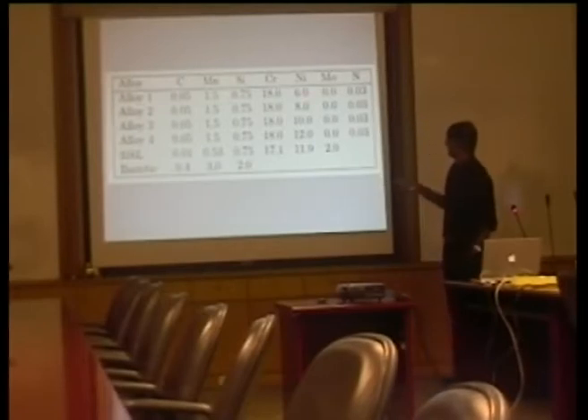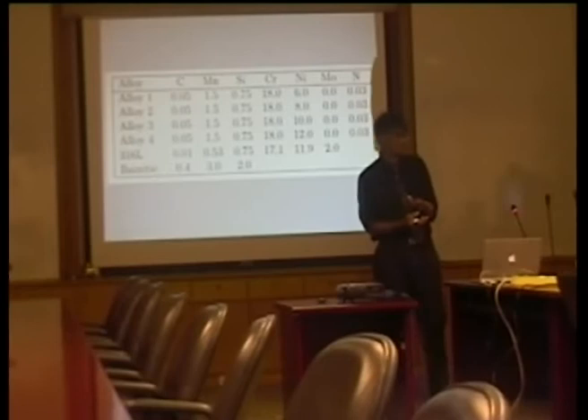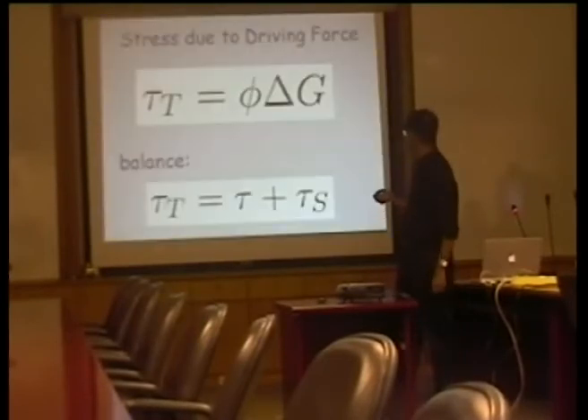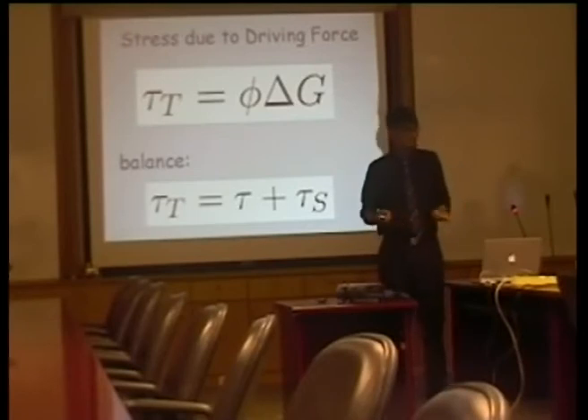So it's very powerful. Bear in mind that here all I'm doing by altering the nickel concentration is making martensitic transformation more difficult, because as I increase the nickel, the austenite becomes more stable. So delta G, the driving force here, decreases when I increase the nickel concentration. So I have alloying element effects in this theory.